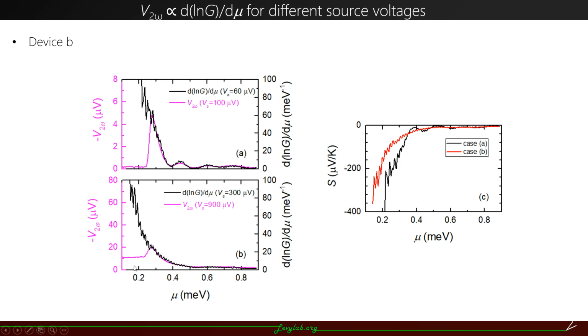We also checked the effect of source voltage. Ideally, we should use as low a source voltage as possible to minimize the thermal broadening effect. But we still need to use a high enough source voltage to get a high enough signal-to-noise ratio. If we increase the source voltage, we see that indeed these quantum features are smeared out, but the thermal voltage still compares very well with d log G / d mu. And if we derive the Seebeck coefficient, they still have the same order of magnitude.